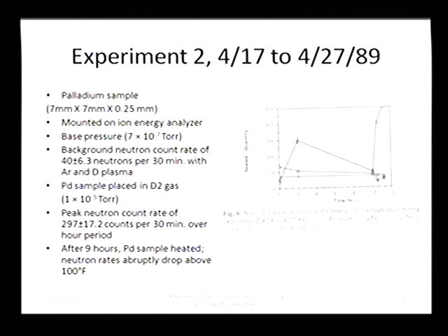Now, the second experiment, which took place in April, this one also used an ion energy analyzer. And in this particular setup, again, we had a base pressure of about 7 × 10⁻⁷. We increased our count rate, did 30 minutes. We did both argon and deuterium plasmas. The plasma action with argon actually helped clean the surface of the palladium. Palladium was placed in the D2 gas at a pressure of about 10⁻⁵ torr, turned the plasma on, and then basically we got a peak neutron count rate of about 297 ±17.2 counts over a 30-minute counting period.